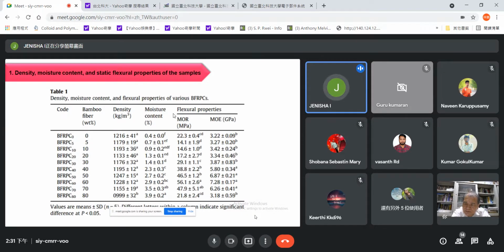So, to understand some of the basic properties like density, moisture content, and static flexural properties, this table is summarized. Here we could see the composite with different loading amounts ranging from 0, 5 to 80 weight percentage. On observing the density of these different composites, we could see that the composite with 80 weight percentage of bamboo fiber shows the lowest density.